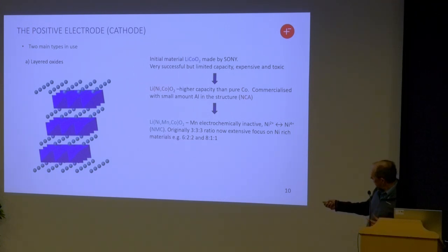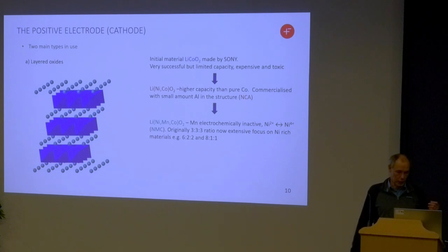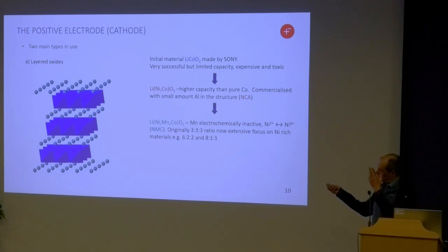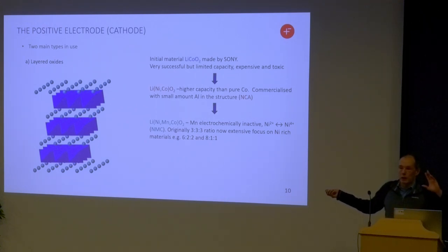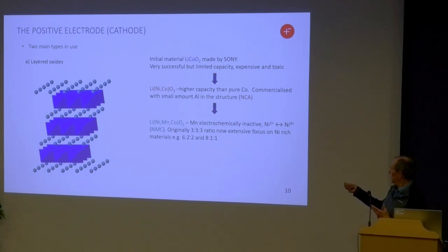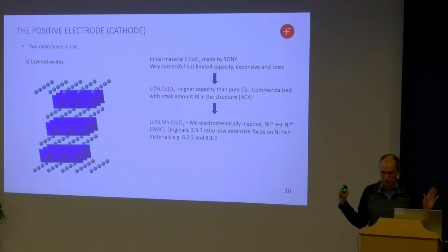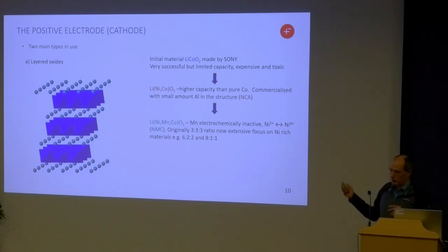What people have done now, they moved on to so-called NMC, nickel, manganese, cobalt. Originally, 1:1:1, 3:3:3, whatever. So in that case, the manganese wasn't doing anything, it was sitting as manganese 4 plus, which it likes to be. Cobalt was going from 3 to 4, as it does in lithium cobalt oxide, and nickel actually goes from 2 plus to 4 plus.